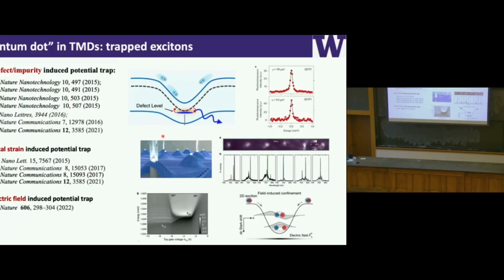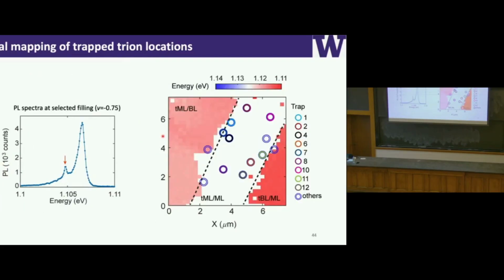It could be because of the interface, the electric field, defects, or strain, but it doesn't really matter for my case because I know there's a trap state, and I'm going to use this trap state to read out the fractional charge. So first, we do a spatial mapping of these trap states. Indeed, we find that these trap states appear at the interface. This dashed line here indicates the interface between the twisted bilayer and the twisted monolayer on bilayer.